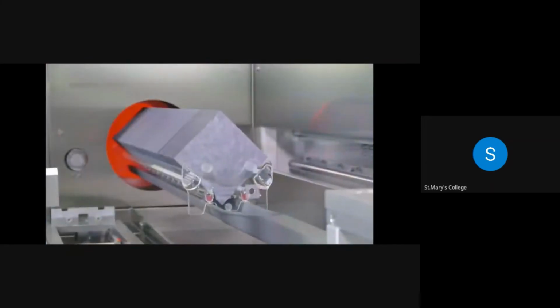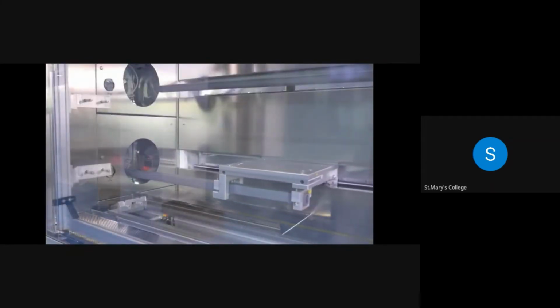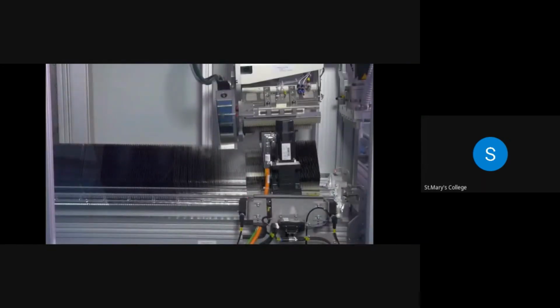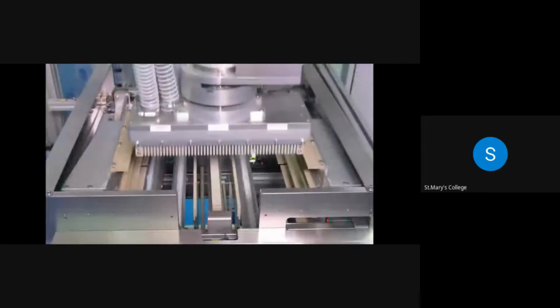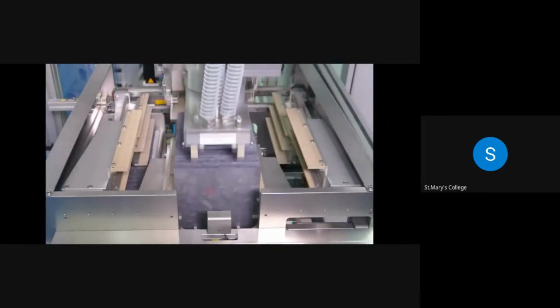Quartz boat with wafers is loaded into the furnace, where diffusion process takes place under low pressure using phosphorus oxychloride. In this process, P-N junction is formed by thermal diffusion in low pressure environment. On completion of diffusion process, wafers are loaded back from quartz boat into wafer cassettes by the robotic system.